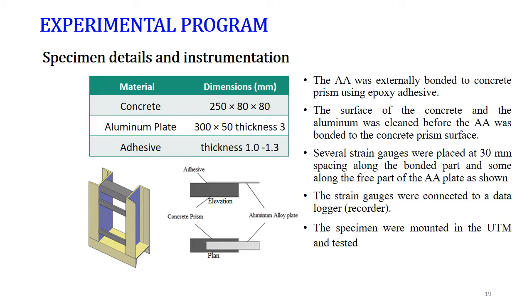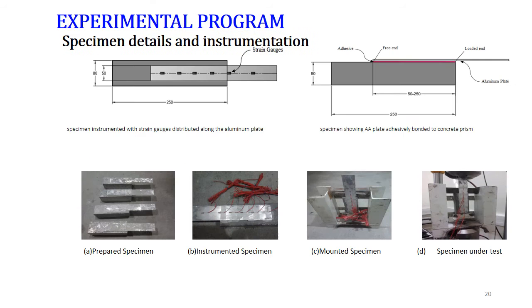The specimen details and instrumentation. Here are the dimensions of the specimen and the aluminum plates. The adhesive thickness ranges between this and this. And here is a typical sketch of a specimen that has been prepared. The setting you see here is for holding the specimen for the direct test. And here you see the picture of it: details of the specimen, instrumentation of the specimen, mounting of the specimen into the rig for the testing, and then putting the rig into the tensile machine in order to carry out the direct shear test.